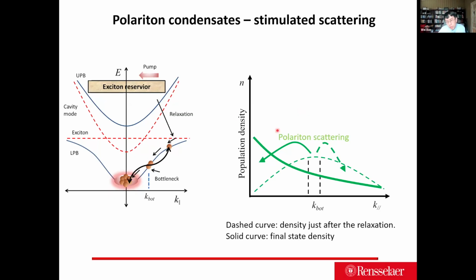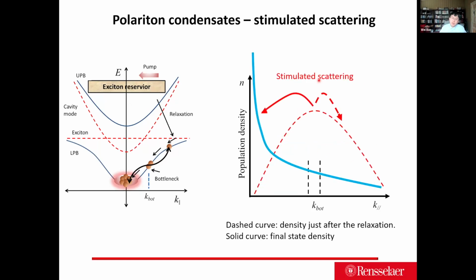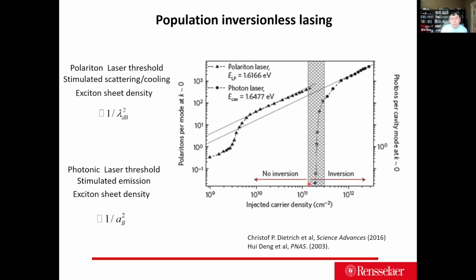And the system relies on stimulated scattering compared with stimulated emission. More precisely, in your bottleneck region, you will have the particles gradually filling the ground state. At the same time, they are scattering into the higher energy state. Such a different mechanism means you can demonstrate a population inversionless laser in the quantum well system and in many other systems.